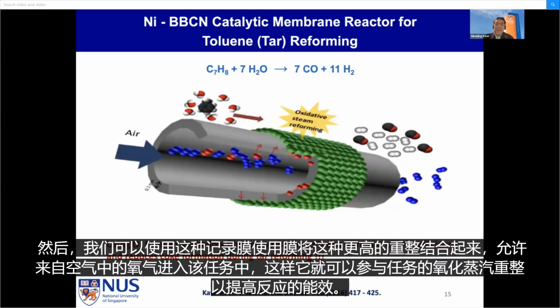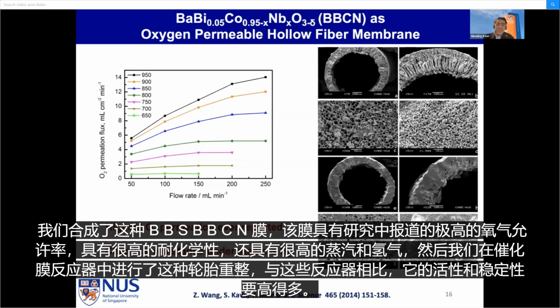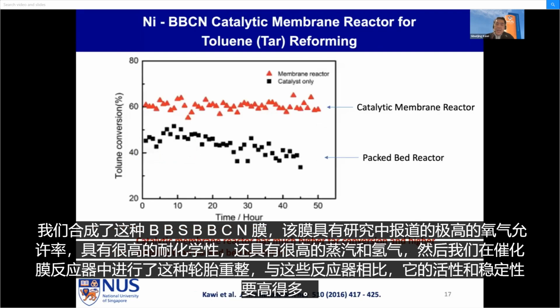We can then combine this tar reforming with a membrane. Using this, we call it a perovskite membrane, oxygen from the air can permeate through the perovskite, so that it can be involved in the oxidative steam reforming of the tar to increase the energy efficiency of the reactions. We have synthesized this BBCN membrane, which has the highest oxygen permeation ever reported in the literature, and it has very high chemical resistance under steam and hydrogen. And we performed this tar reforming in the catalytic membrane reactor, which shows much higher activity and stability compared with the packed bed reactor.